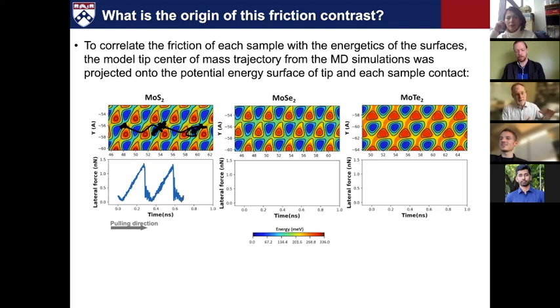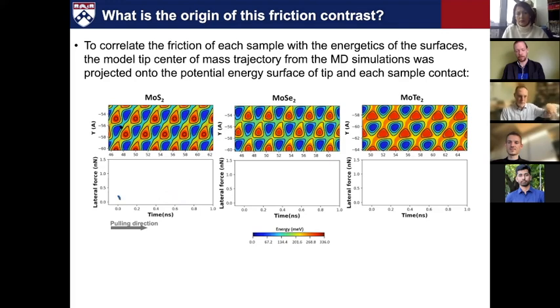they associated that with the fact that, I brushed off the difference in potential energy surface, but there is a small difference. The telluride does have a slightly higher corrugation than the selenide, which is slightly higher than the sulfide. And when it's layer on layer, you don't get to take advantage of this saddle effect in the same way that you do with a tip. And so in their case, the friction contrast inverted. So tip on layer has a different trend than layer on layer. There's an interplay there between corrugation, lattice constant, and perhaps the mechanics and the stiffness. So, just some food for thought.